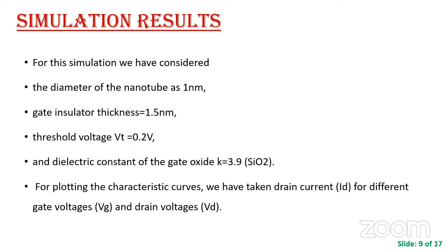So we have simulated this by using the NanoHub tool, and in this simulation we consider the diameter of the nanotube as 1 nanometer, the gate insulator thickness 1.5 nanometer, and the threshold voltage is 0.2 volt. The dielectric constant for the gate oxide is 3.9 of SiO2. For plotting the characteristics, we have taken different drain currents for different gate voltages and drain voltages.